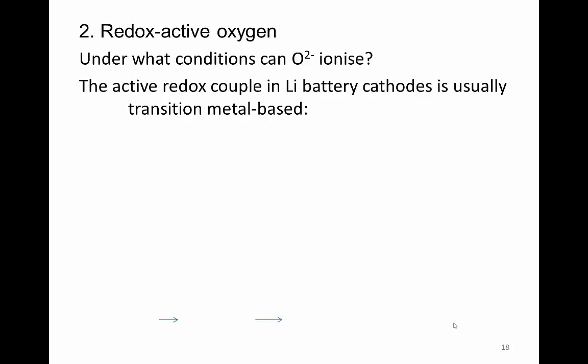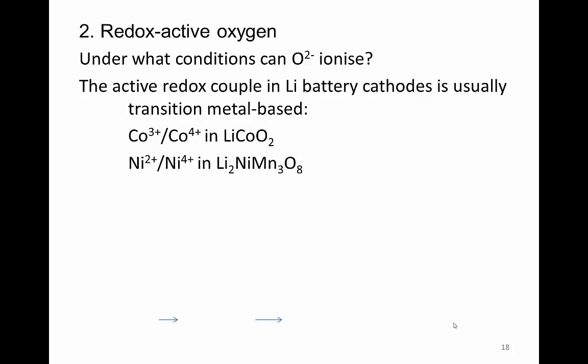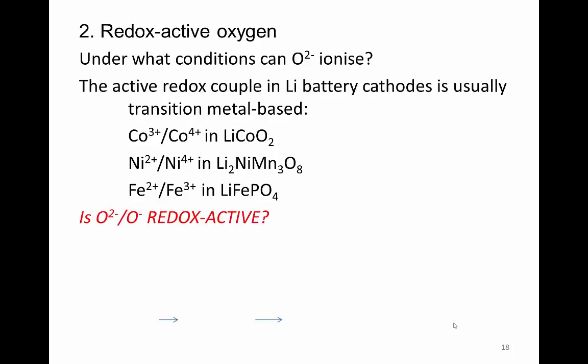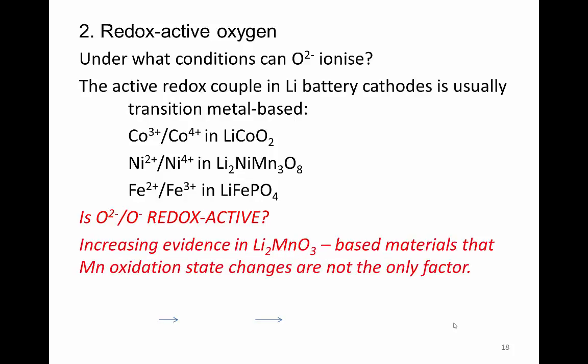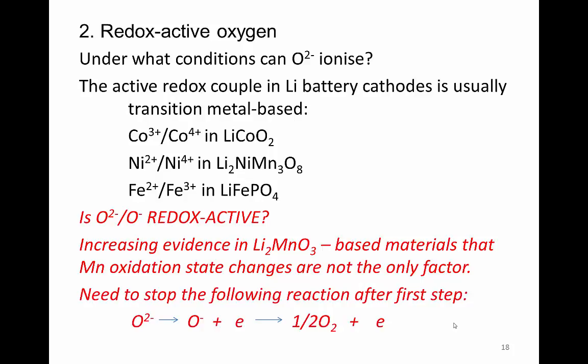So the redox active couple in lithium battery cathodes is usually the transition metal. And so we've seen the examples of cobalt 3+, 4+ in lithium cobalt oxide. There is nickel 2+, 4+ in this lithium nickel manganese oxide spinel. There is iron 2+, 3+ in the lithium iron phosphate. And the question then is, well, can O2 minus going to O minus also be a redox active component? So it's not a metal, but if we can get reversible redox activity of oxygen, then the advantages or the possibilities of this are that this can give rise to increased capacity in our cathode material.